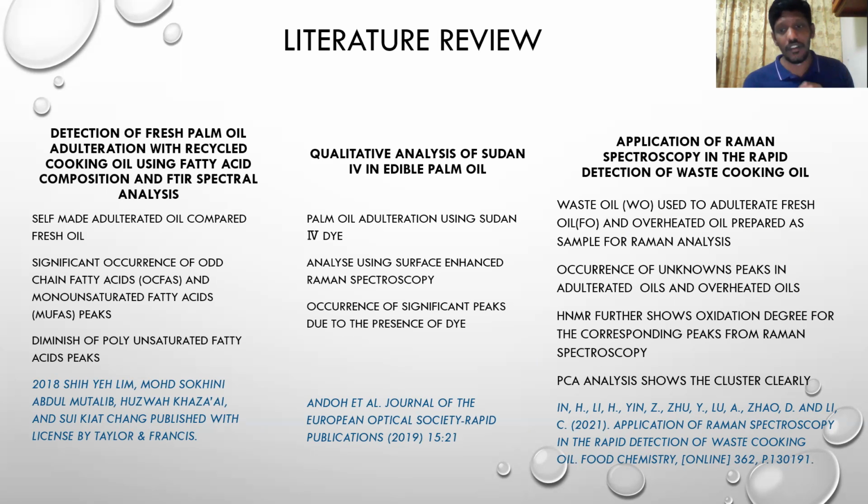Then this oil was further processed to become recycled oil, where deodorization, degumming and bleaching were performed. Then this recycled oil is mixed with fresh oil in ascending order of concentration, and FTIR analysis is performed. The outcome of this experiment is the significant occurrence of odd chain fatty acid and monounsaturated fatty acid peaks, and also the diminishing of polyunsaturated fatty acid peaks.